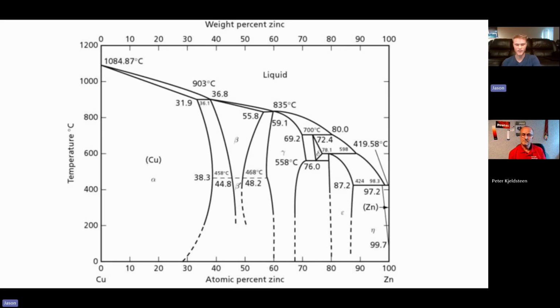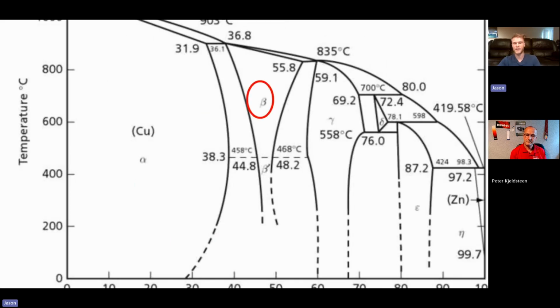So if we look at just the copper-zinc phase diagram, we see something very familiar in this region. And so I want to focus on the beta phase and the alpha phase. If we look in this region, we have a very similar looking pattern, right? We have beta, which is a solid phase, alpha, also a solid phase, and then we have an alpha-beta coexistence region between the two. Now, beta is a high zinc phase, alpha is a low zinc phase. And so the thinking is we could have a process very similar to the formation of kamacite from taenite in this material system. We could instead have a formation of alpha from beta.